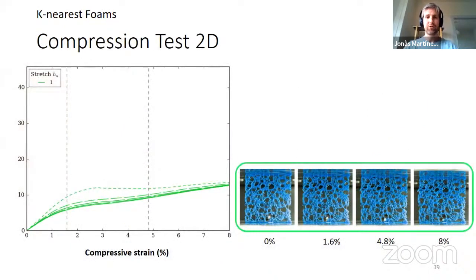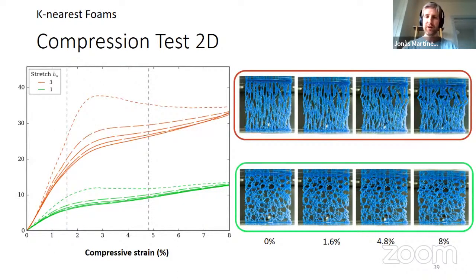We also did some compression tests, and here is where some issues arise. As you can imagine, if you have something that is highly stretched in one direction and you start straining it, at some point you will have buckling, because the elongated fibers are going to start to buckle. So what you can see here, this sudden drop, is due to buckling.